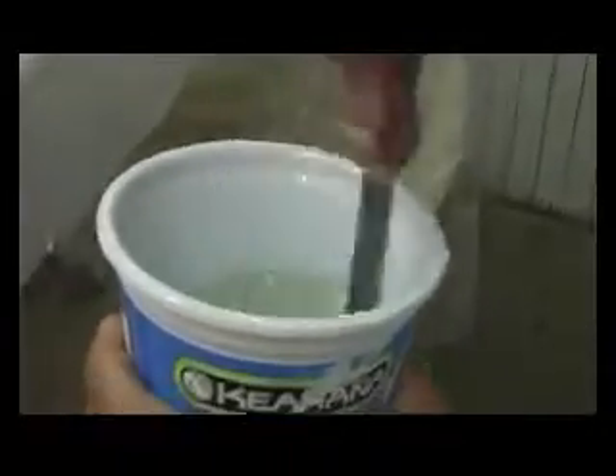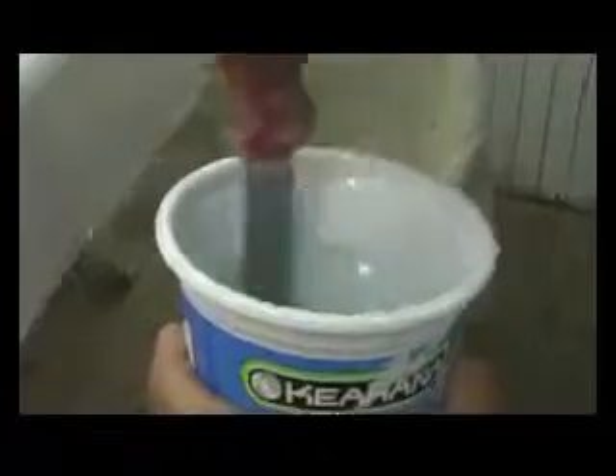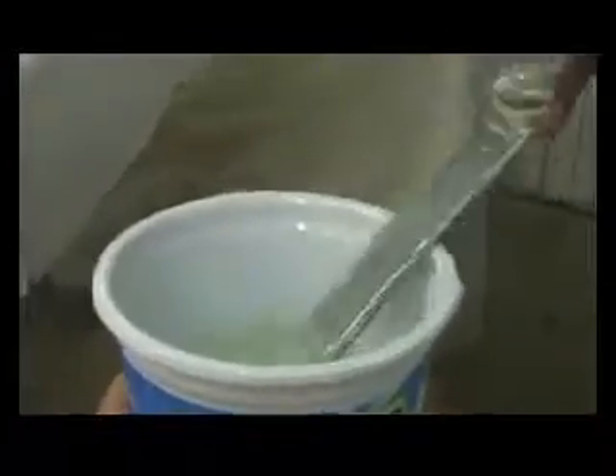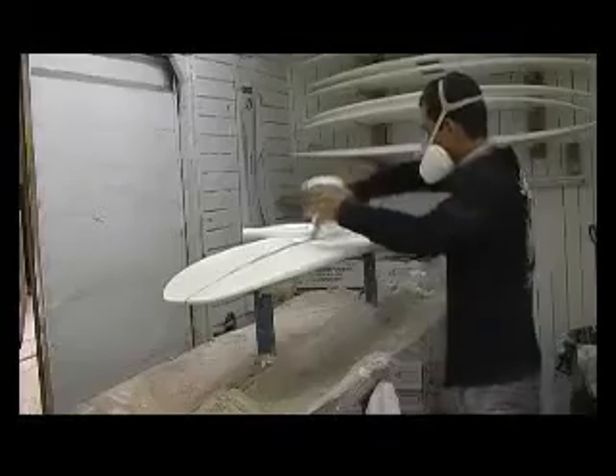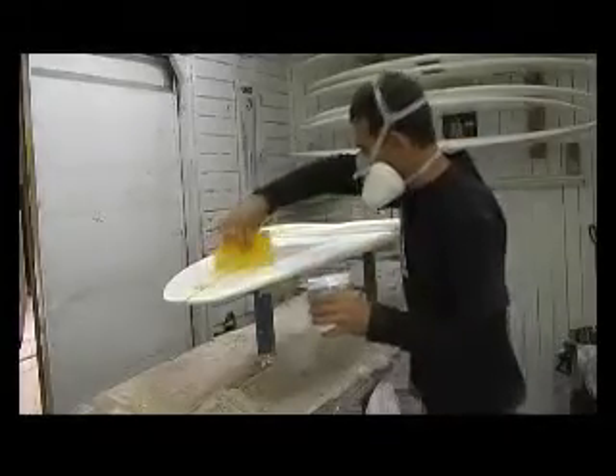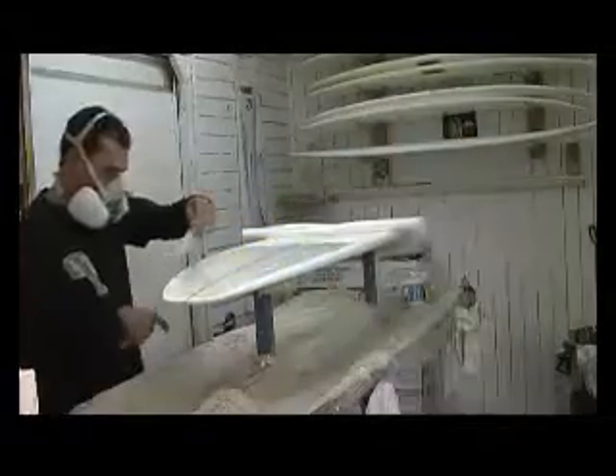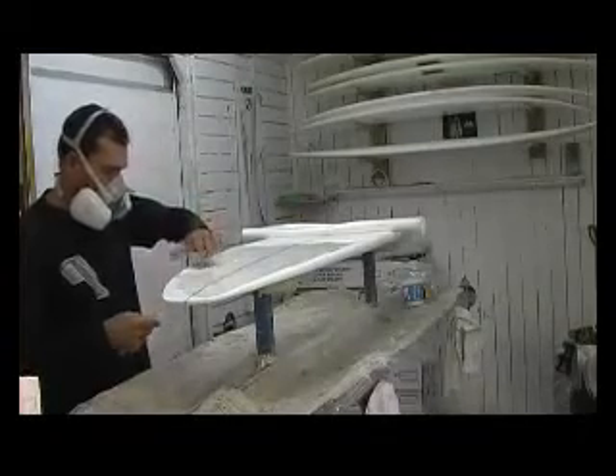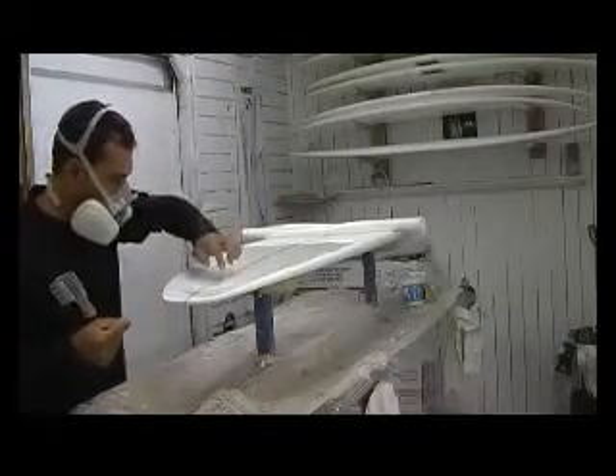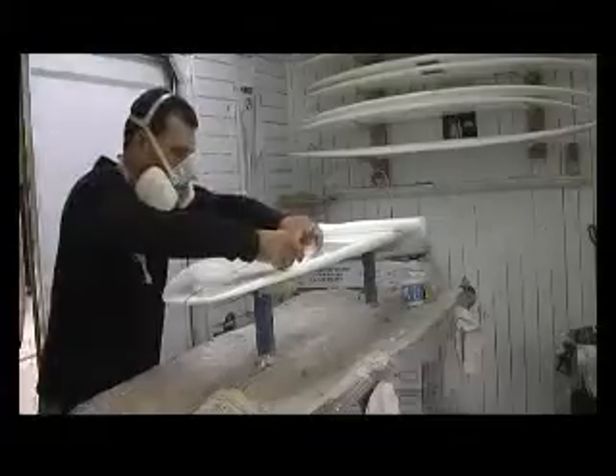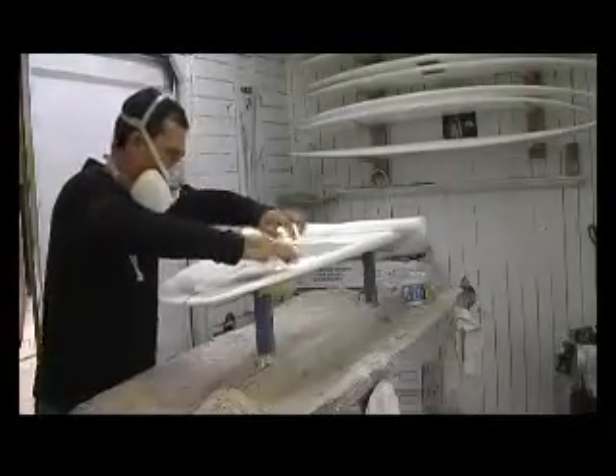Put the resin from the sachet into the hardener pot, labelled number 3, glassing bottom, and mix it up for 2 minutes, ensuring the entire pot is well mixed. Cut 3 pieces of cloth measuring 15 cm by 8 cm to use as reinforcement for the fins. Place them where the fins will be installed.